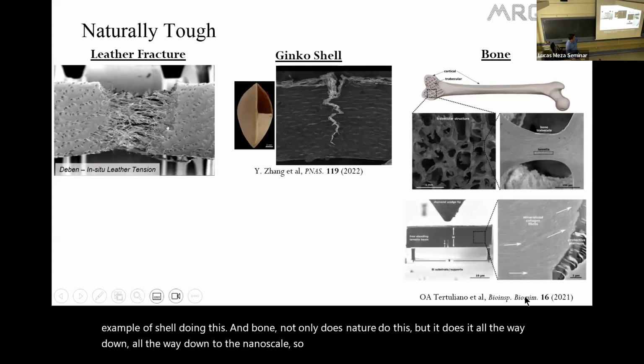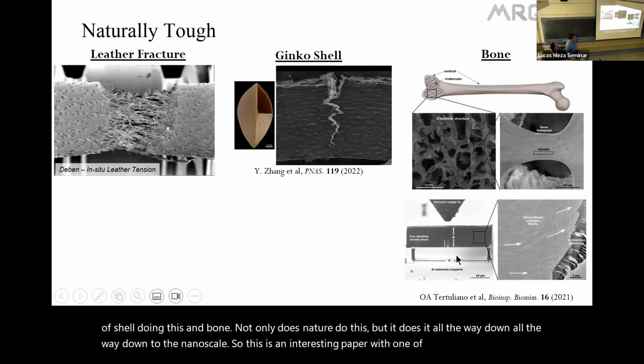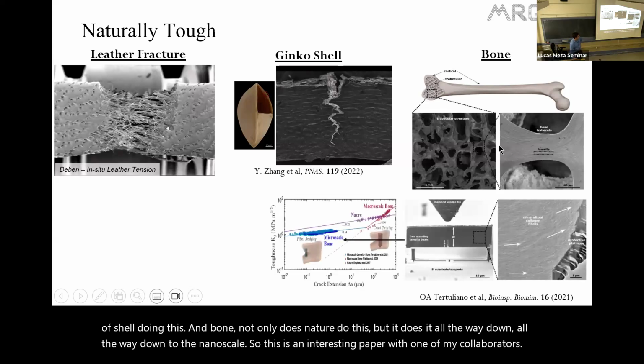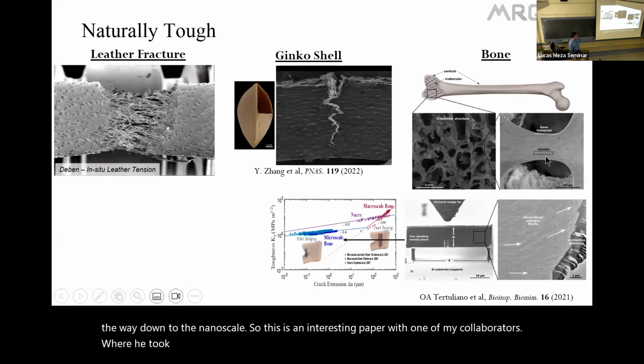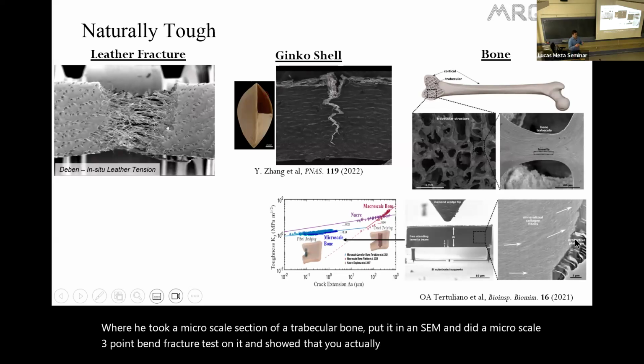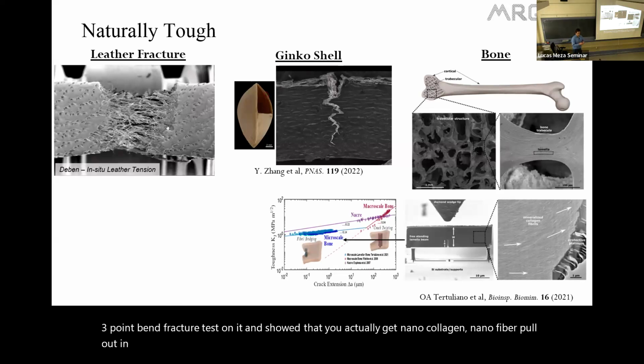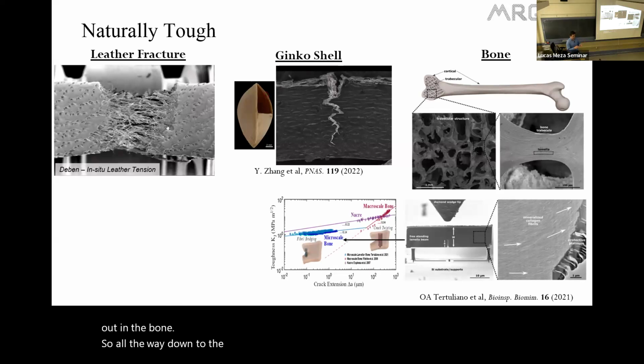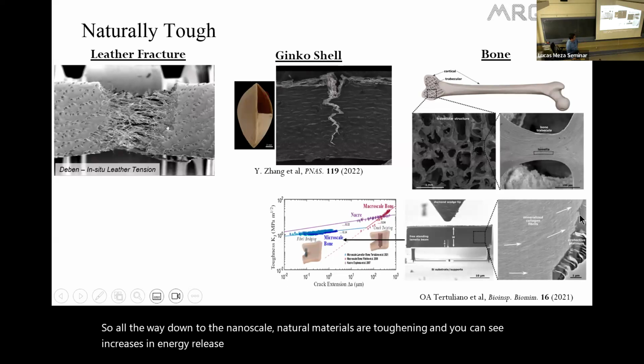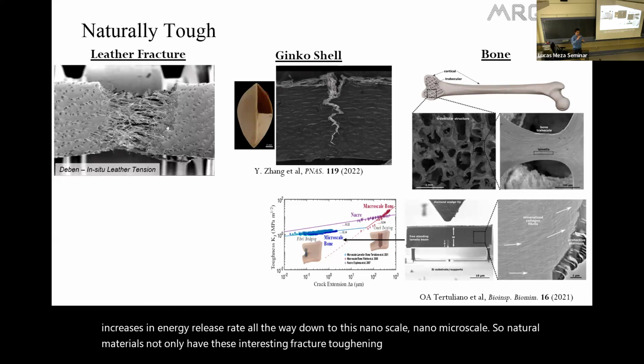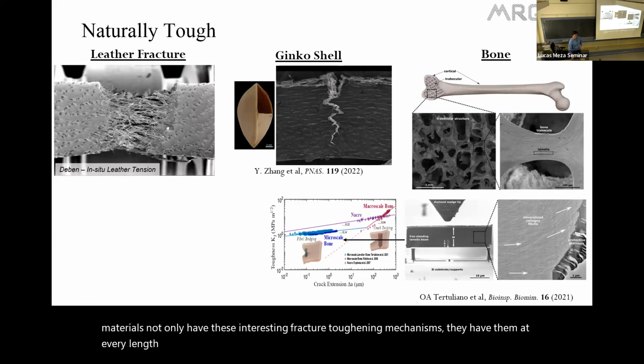So this is an interesting paper with one of my collaborators, Otmar Tertuliano, now at Penn, where he took a microscale section of a trabecular bone, put it in an SEM and did a microscale 3-point bend fracture test on it, and showed that you actually get collagen nanofiber pullout in the bone. So all the way down to the nanoscale, natural materials are toughening. And you can see increases in energy release rate all the way down to this nano-microscale. So natural materials not only have these interesting fracture toughening mechanisms, they have them at every length scale, all the way down to the nanoscale.